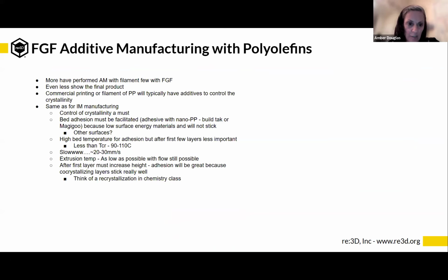All right, so I kind of talked about this a second ago. There's been more people that have performed additive manufacturing with filaments than there have been with FGF. There's been a couple of papers I've seen published, and they are going through each parameter, and each parameter is important, but the two main important temperatures are the bed and the extrusion temperature, and the rate that you're printing at. The slowest you can, the best.